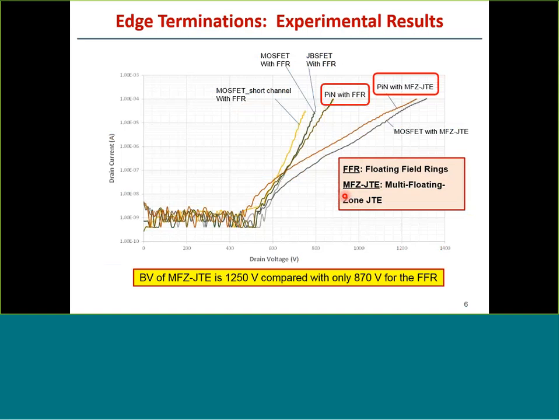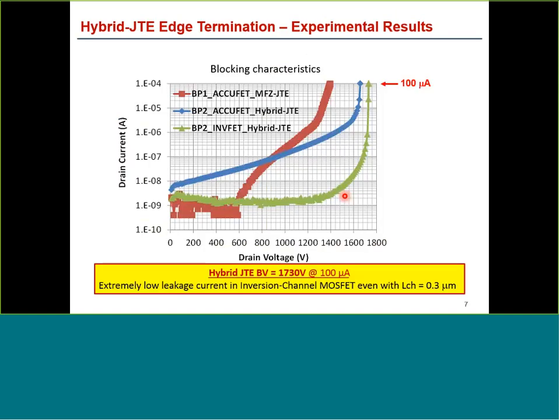We did some early work in BP1 to compare the floating field ring with the multiple floating zone JTE, and you can see from this chart that the breakdown voltage with multiple floating zone is 1250 volts compared with only 870. But things got even better once we introduced the hybrid JTE. And with this termination, you can see that with the inversion mode MOSFET, we get a very low leakage current, and the breakdown voltage is 1730 volts for our devices.